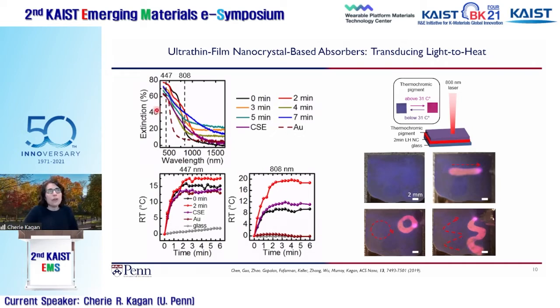And so at short wavelengths you can get absorption in gold, but not at long wavelengths. What we were interested to see is that as we control the degree of exchange, just by controlling the time that we immersed it in the solution, we could control the extinction of the material. For example, for a short exchange time, if you look at the example here at 808 nanometers, there's actually a fairly large extinction in the nanocrystal film, something that you don't get in the bulk material.